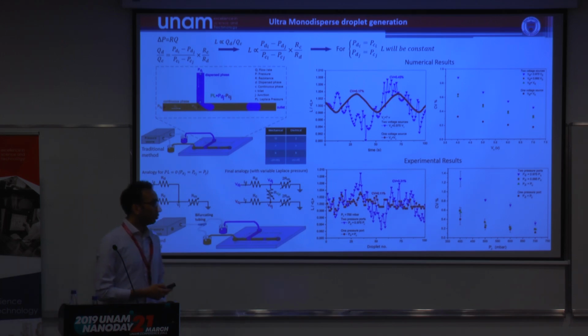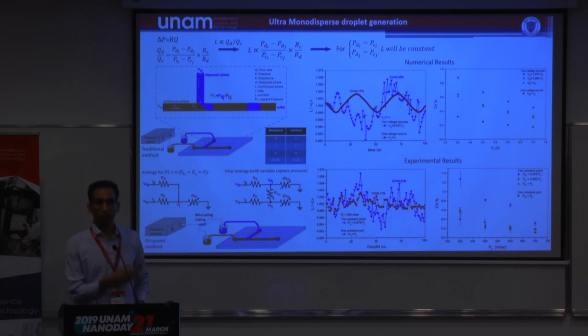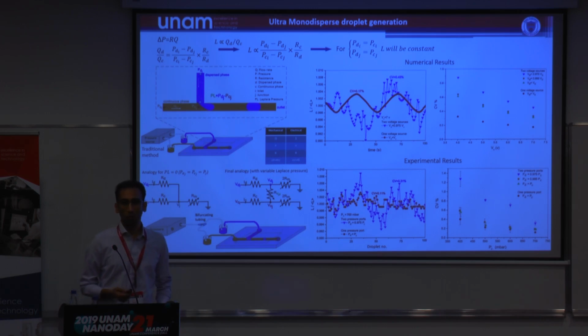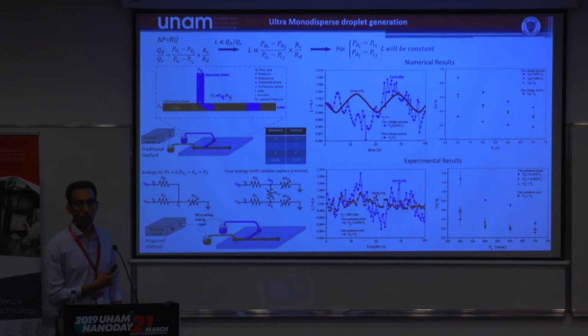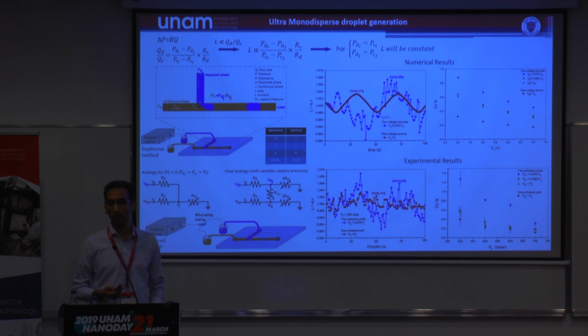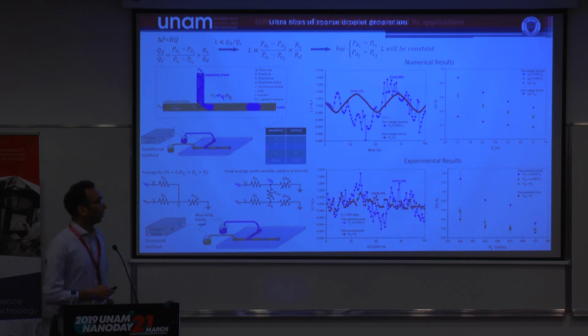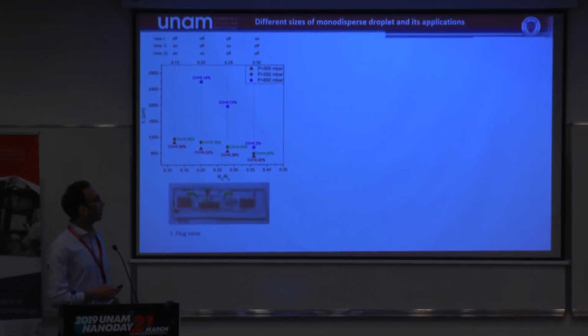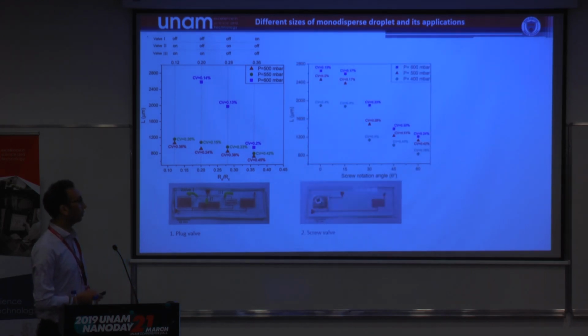Then we tried to make those monodispersed droplets in different sizes. But how? Because we are using one single port and we are supplying identical pressure, so we cannot change the pressure. So we came up with this idea. By changing the hydrodynamic resistance of those channels, we can change the size of the droplet. We used two different techniques.